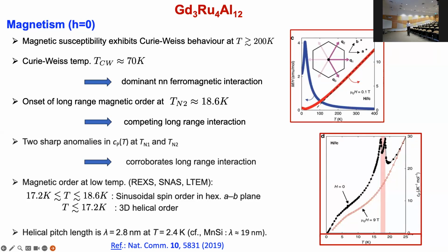Interestingly, the helical pitch length is 2.8 nanometers. This is what determines the size of the skyrmions when they are stabilized. Compare that to manganese silicide, where the pitch length is 19 nanometers. So there is almost a factor of 6 to 7 between the pitch lengths, and you already see that it favors small skyrmions.